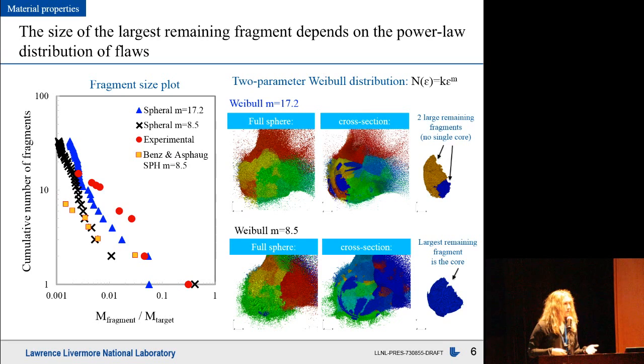After Benz and Asphaug had done this scan and found M equals 8.5 to be the best parameter match, Nakamura went back and measured the K and M parameters for the Yakuno basalt used in this specific gas gun experiment, where she found the exponent M to equal 17.2, which could mean very big differences in our simulation results since M is an exponent.